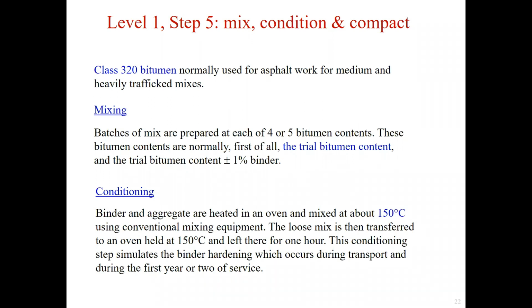The aggregate and binder are heated in an oven and mixed at 150 degrees. The mix is then transferred to an oven and conditioned at 150 degrees for 1 hour.